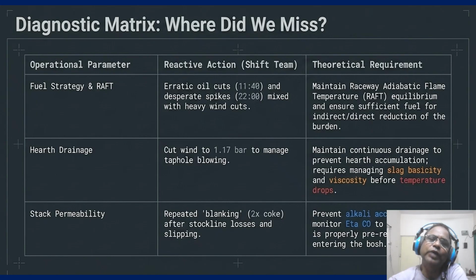Finally, look at the stack permeability. They kept blanking with the coke but failed to address the root cause: alkali accumulation. The so-what factor is the gap between reactive and theoretical operation. If you only react to the symptom, like a wild cast, without understanding the underlying raft or viscosity shift, you will almost always choose the wrong lever to pull. Let's dive deeper into the first major miss, the total loss of the thermal balance and the raft control.